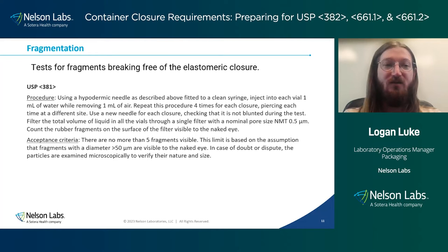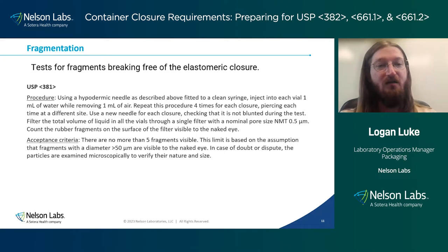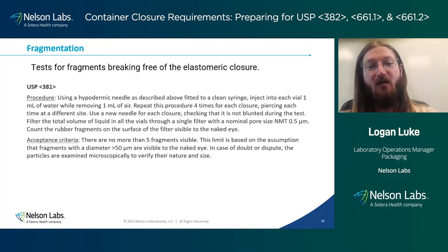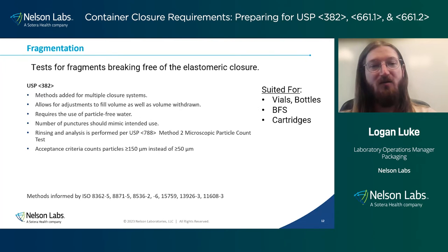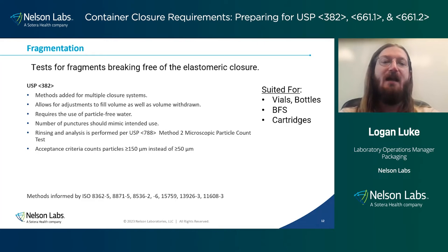If you look at the original USP 381 method, the acceptance criteria originally asks to find fragments that were greater than 50 microns, and that was what was considered to be visible to the naked eye. But if we go here to USP 382, well, one of the things that's different is that bottom bullet there, where the acceptance criteria is now counting particles greater than or equal to 150 microns instead of that 50. Additionally, there are multiple methods for different closures, like we talked about.